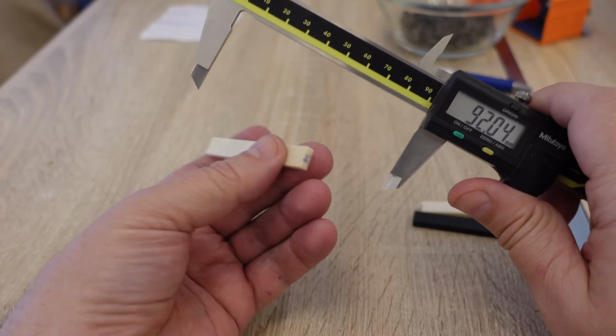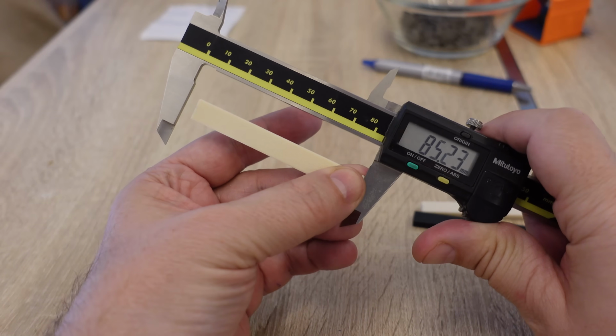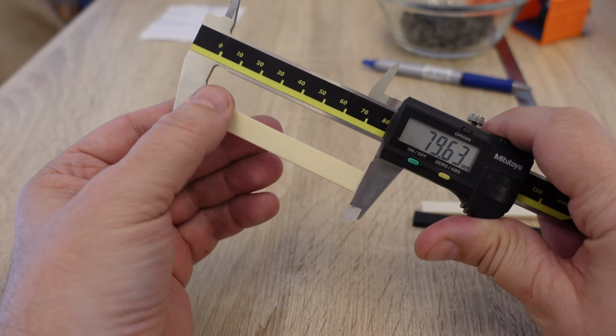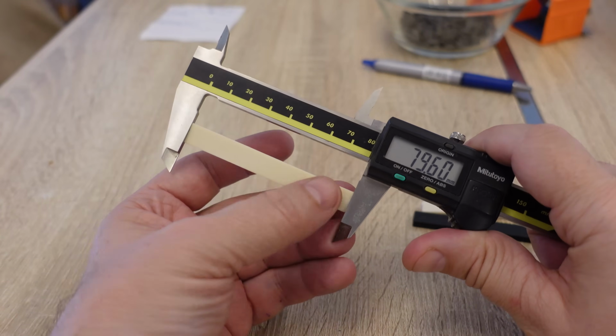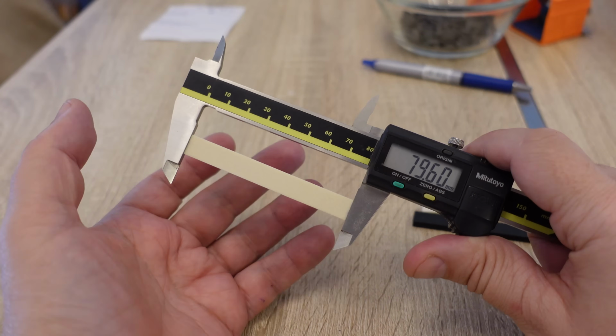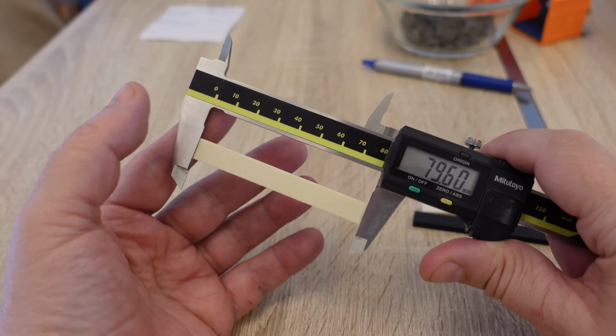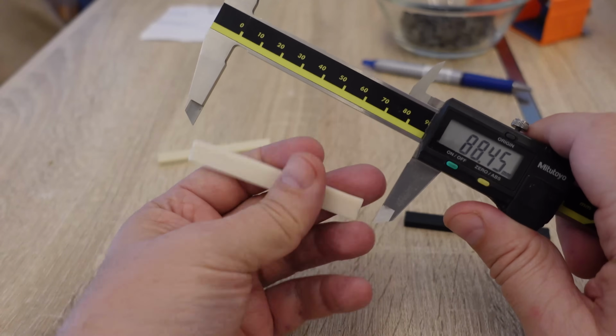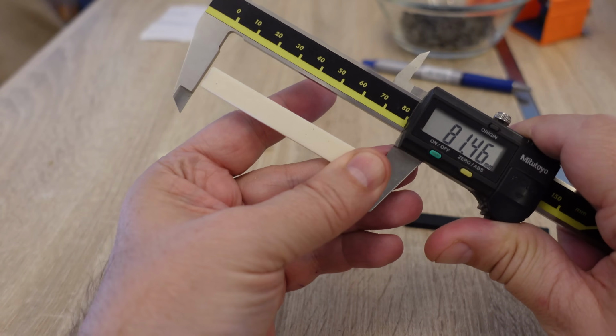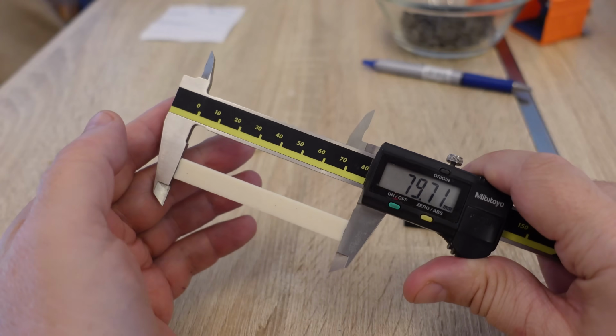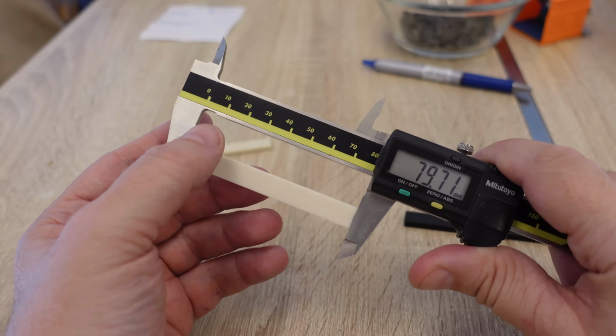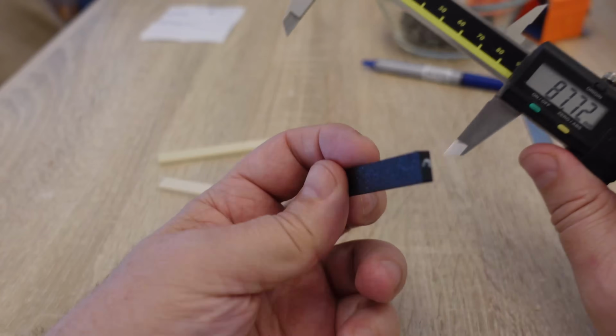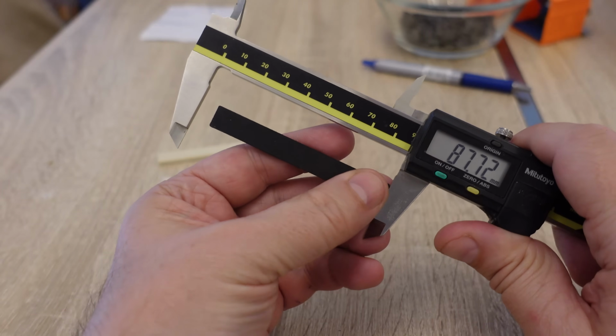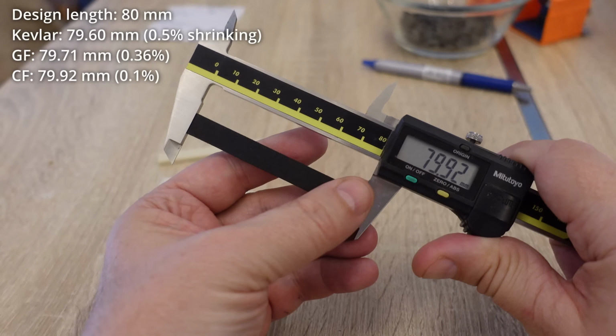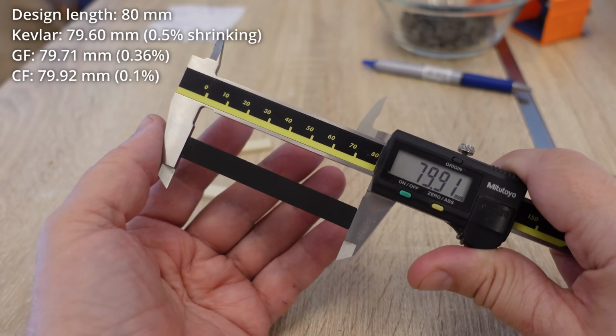Let's measure the shrinking. This is Kevlar. And I noticed some elephant foot, so I'm measuring above it. 79.60. This is basically very similar to the average ABS or ASA without fibers. This is the glass fiber version. 79.71, so less shrinking with this one. And the carbon fiber version. 79.92, so the smallest shrinking with the carbon fibers.